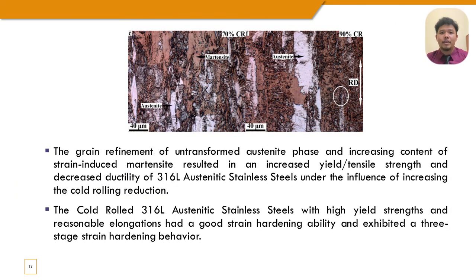Next, the grain refinement of untransformed austenite, together with an increasing content of strain-induced martensite, resulted in increased yield and tensile strength and decreased ductility of 316L austenitic stainless steel under the influence of increasing cold rolling reduction. Last but not least, the cold rolled 316L austenitic stainless steel with high yield strength and reasonable elongation had a good strain hardening ability and exhibited a three-stage strain hardening behavior.